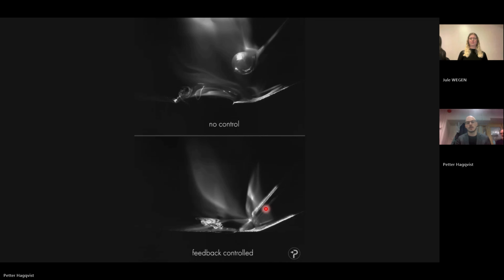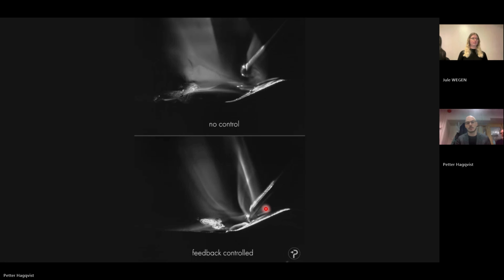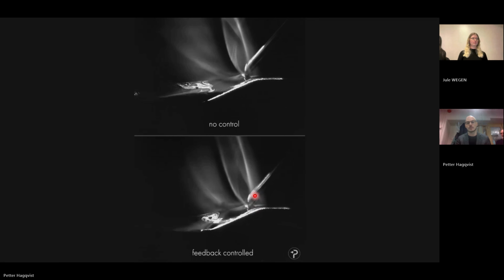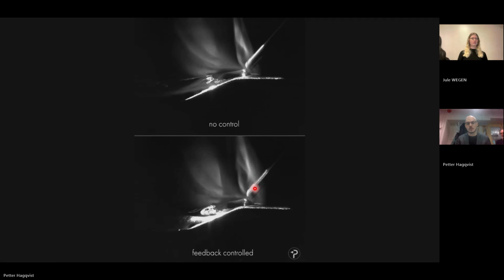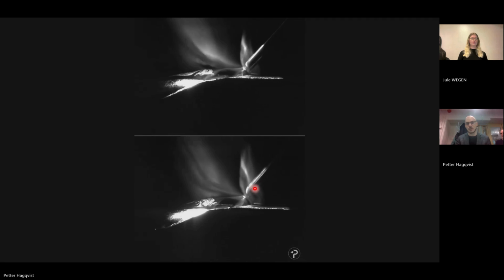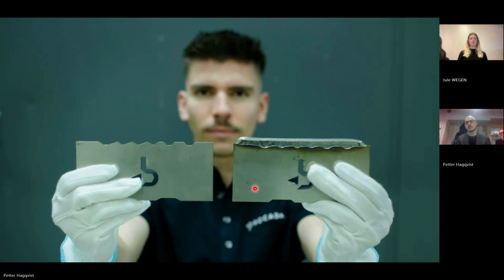The wire is actually, if you look carefully now that we're going back up again, you can see that the wire is moving upwards. So the actuator is constantly adjusting the position of the wire to follow the substrate surface. And this is what it looks like when we're done. So to the left here, you see the profile that we try to follow. And to the right, you see what it looks like when we're done. So we're not only able to follow and maintain a good process, we're also able to smooth it out or repair it.